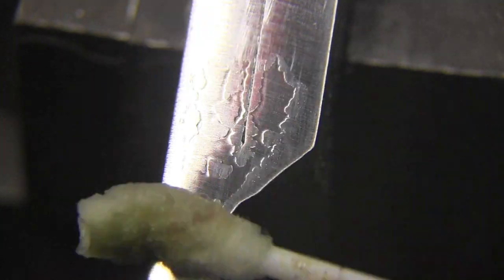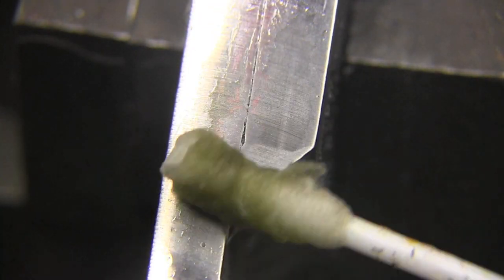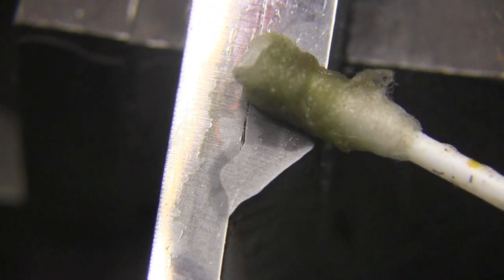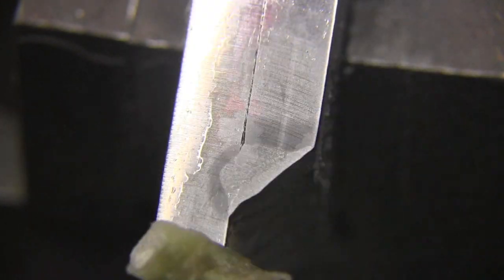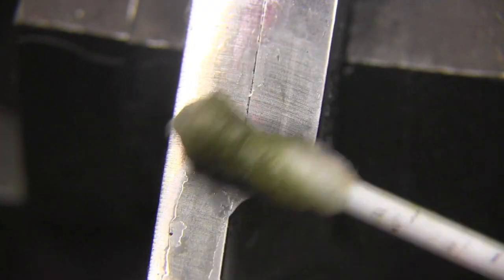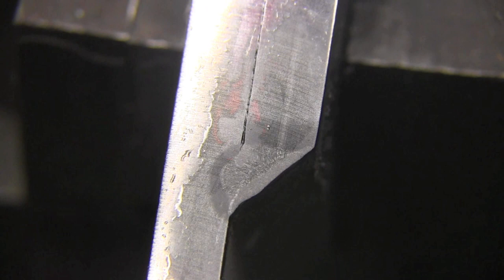So let's check that out and throw a little swab etch on that thing. And actually it's quite a bit better than the hotter setting just because of it slowing the travel speed down. That's actually not too bad right there. I see a little lack of fusion right in the root of the joint, but that's pretty typical